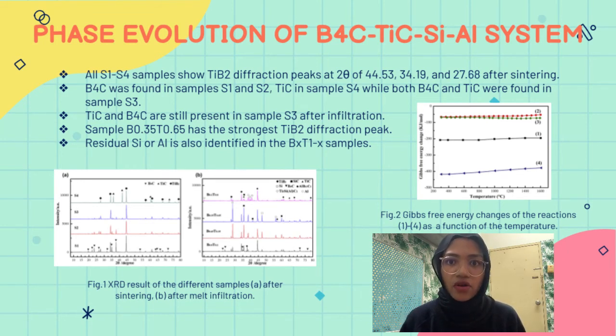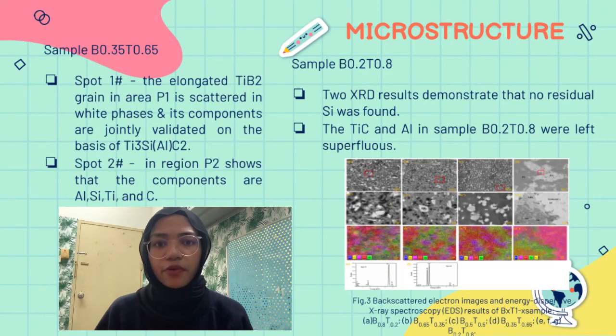Due to the correct boron-titanium atom ratio of raw powders, sample B0.35T0.65 has the strongest titanium diboride diffraction peak. According to the EDS result of sample B0.35T0.65, spot 1, the elongated titanium diboride grain in area P1 is scattered in white phases formed of titanium, silicon, aluminium and carbon elements, and its components are jointly validated as Ti3SiAlC2 determined by the XRD. The EDS result for spot 2 in region P2 shows that the components are also the same as P1. However, the XRD results of sample B0.2T0.8 demonstrate that no residual silicon was found. As a result, the titanium carbide and aluminium in that sample were left superfluous.